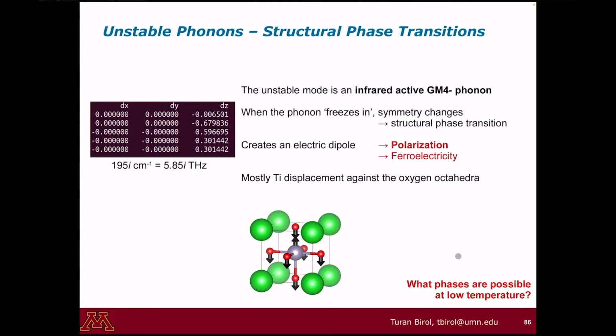Okay. Now, I know that the space group of barium titanate is Pm-3m, number 221, at high temperature. We have seen the cubic perovskite structure. We plugged it into that FindSym tool earlier in the morning. But at low temperature, since there are these atomic displacements, some symmetries must be broken. And most importantly, for example, inversion symmetry is broken.